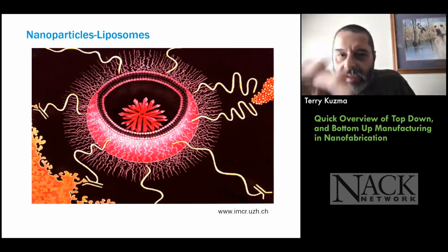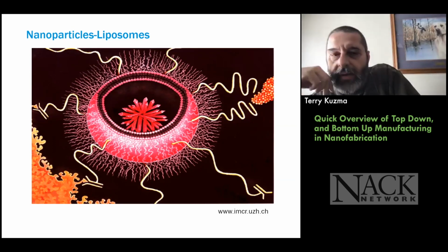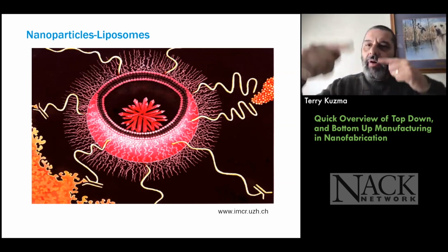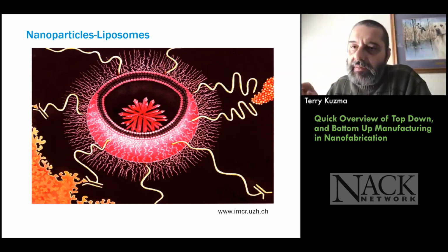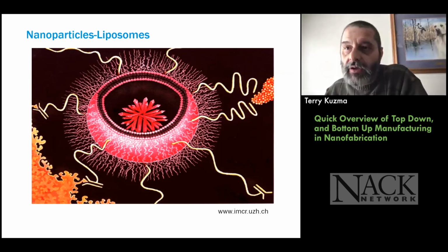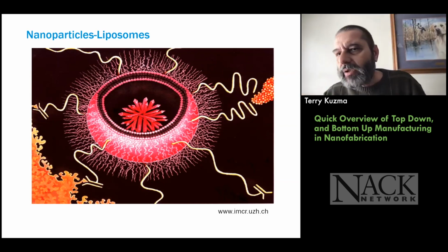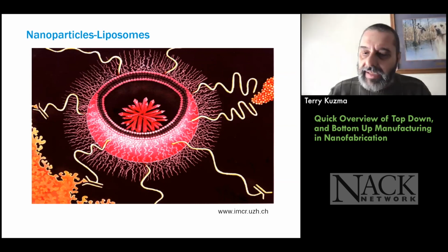If you put a naked liposome in, it would be out of your body in 20 minutes. If you put the sugar on there, that pink fur, and it's probably not pink, it'll stay in for a few days. And you need time for it to drop into, at least in what I teach with the mindset I'm looking at, a cancer drug, it would go into the defective endothelial cells in the cancer region. How about that? That's neat stuff.